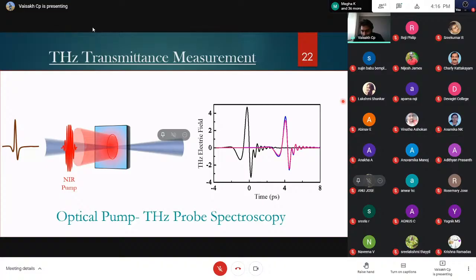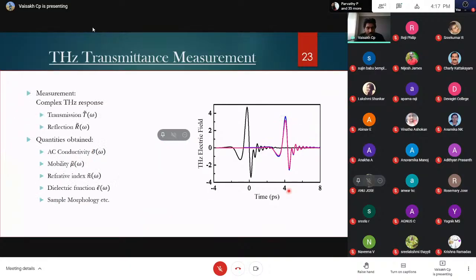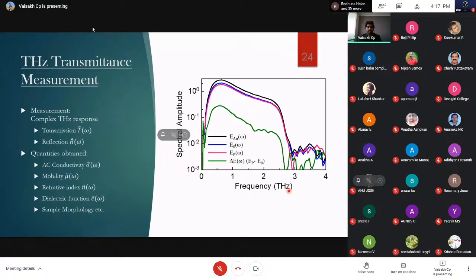So you can see readily that the red pulse has a slightly lower amplitude than the blue due to terahertz radiation absorption by the electron-hole pairs. And one could vary the time difference between the excitation and probing, and such spectroscopic arrangements are called optical pump terahertz probe spectroscopy. So by comparing these pulses, by looking at their FFT spectrum and